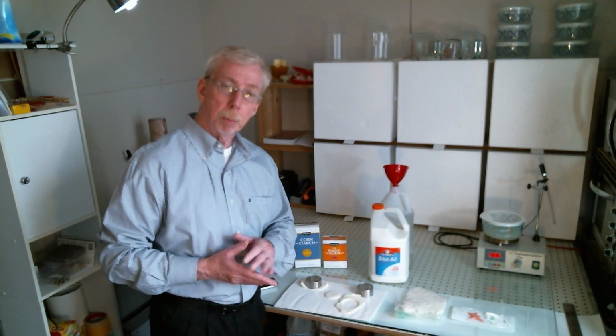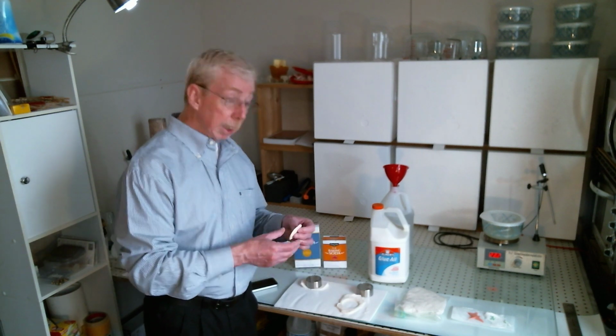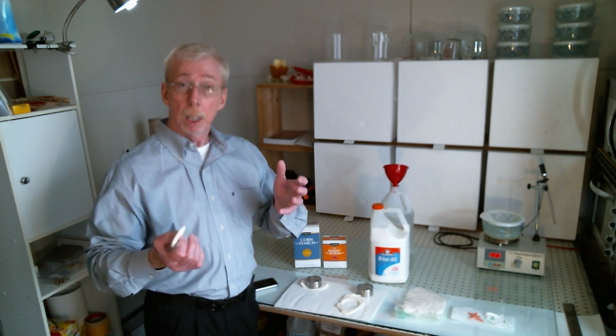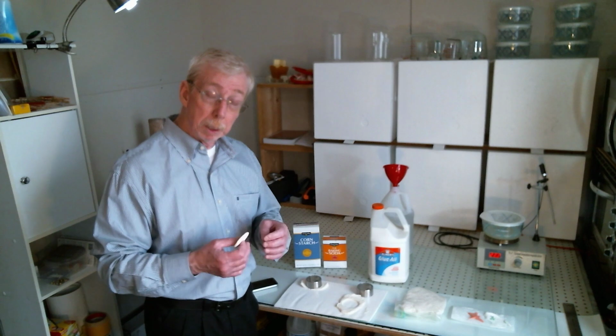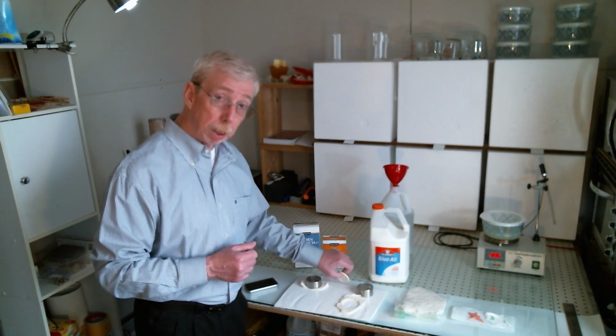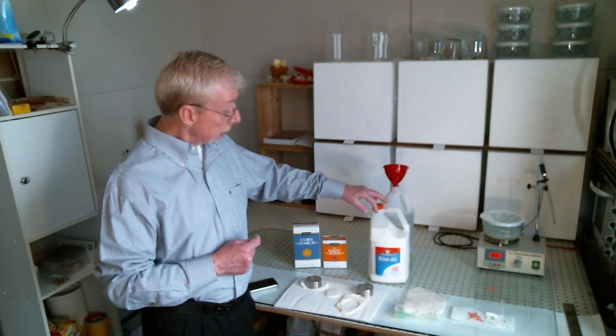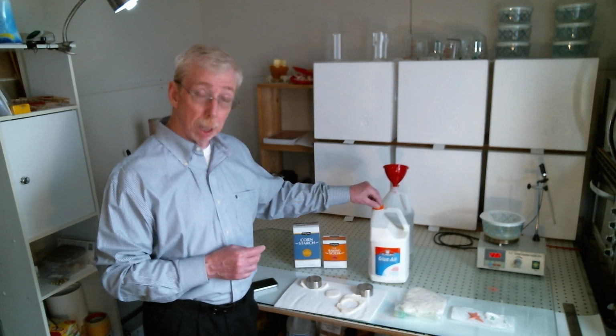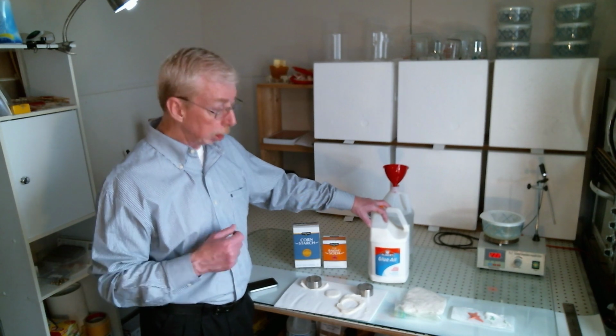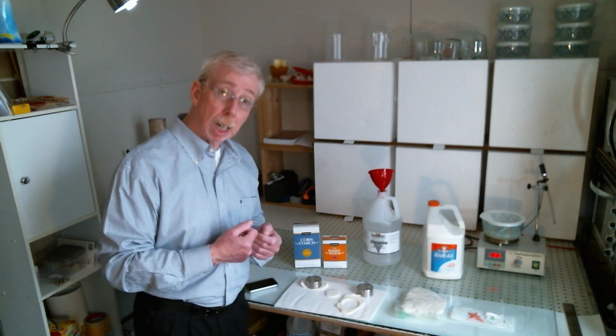All right, so we've reached the point now where we can examine some results here. Semi-flexible. Now this is not exactly cold processed porcelain, and I'm going to continue. I'm inspired enough to continue on and perhaps make another video, perhaps two, in a series of steps to reformulate cold processed porcelain. But we know now that we can eliminate the PVA. Now, the culprit in the PVA is the water. There's a lot of water in this, and that is what's giving us the shrinkage. So we can eliminate that, and we can use glycerin as the plasticizer.